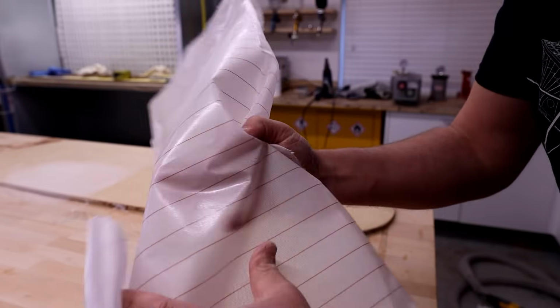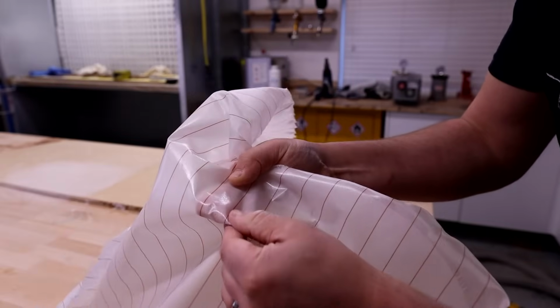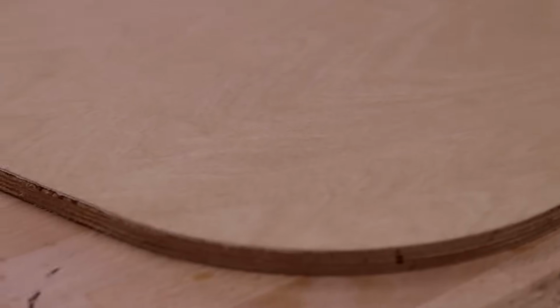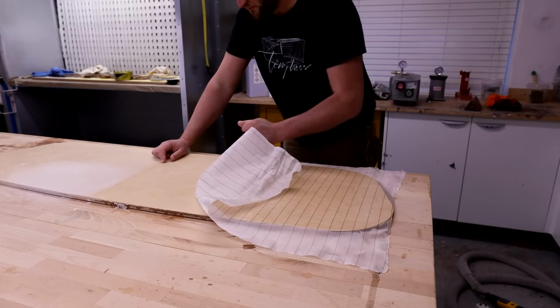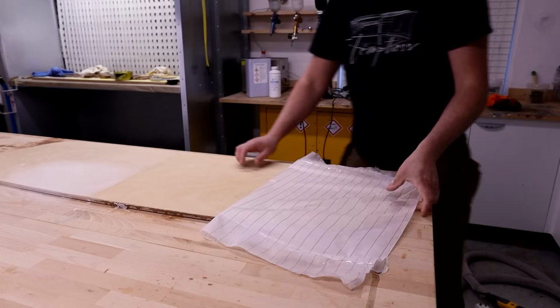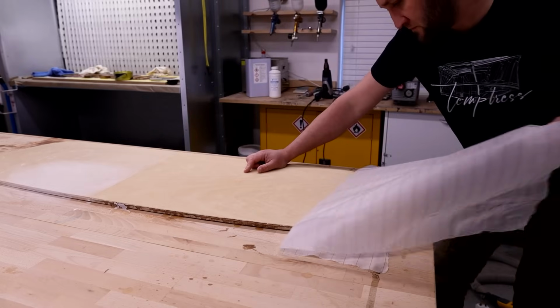This takes with it any excess of resin. It leaves behind a uniform textured surface beneath. And this is the equivalent to a surface sanded to 80 grit roughness, ideal for bonding to. As this involves peeling off the top layer of the resin, it takes with it the amine blush that resides on the top surface. This solution leaves you with a surface that is blush-free, correctly abraded for further bonding, and completely clean.